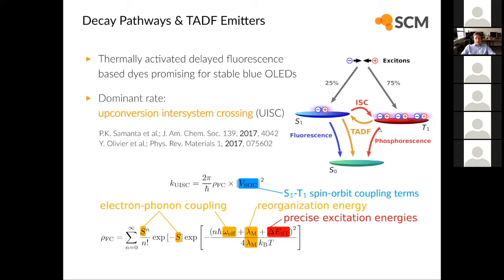Also, there's a recent example about so-called third generation OLED materials, which basically try to increase the efficiency of such OLED dyes. The main thing here to keep in mind is that if electrons and electron holes, as said already before, meet in the OLED layer and are located on a single OLED dye molecule, they basically translate into excited states, and there is a 75% chance for this state to be of triplet multiplicity and only 25% for that state to be a singlet state.